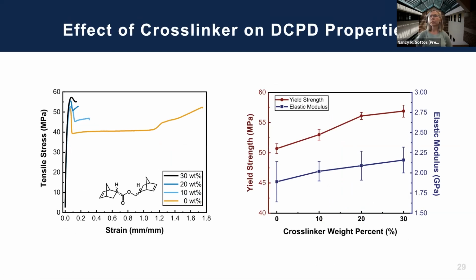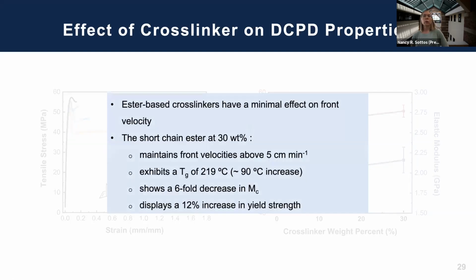Again, the amount of crosslinker, of course, is also affecting the mechanical properties, so the ductility of the polymer is going down, but it's still pretty tough. Yield strength is going up with crosslinking, and elastic modulus is also going up with crosslinking, as you might expect of the neat resin. We've also incorporated, so just to summarize that quickly, these ester-based crosslinkers have a minimal effect